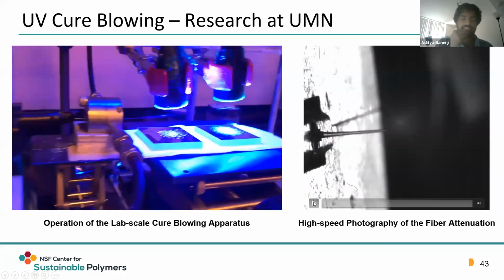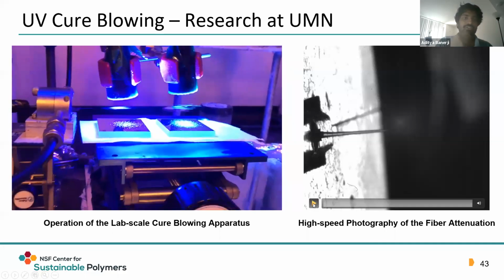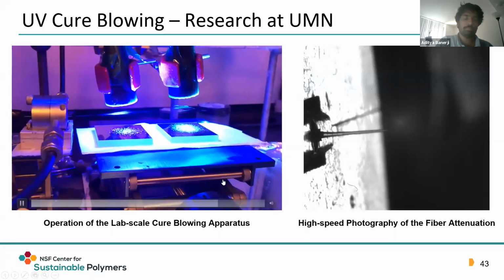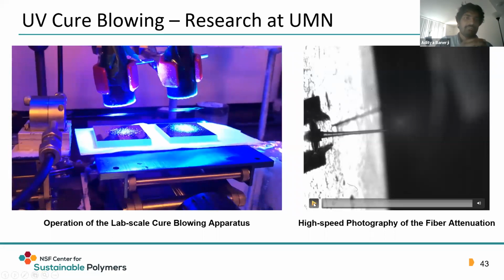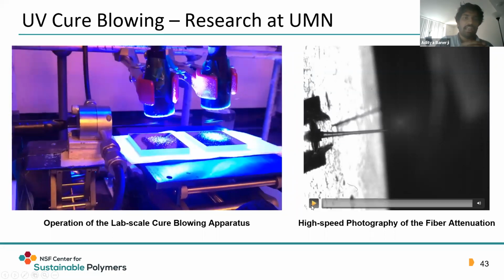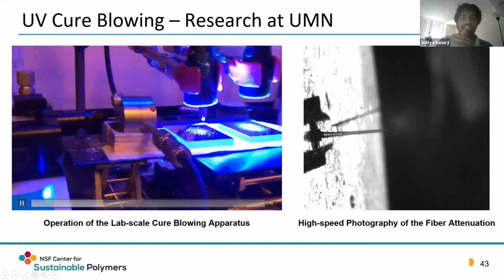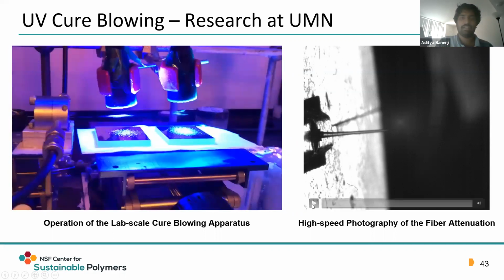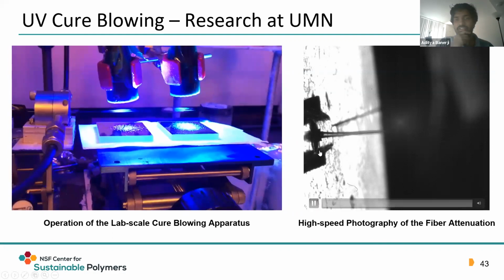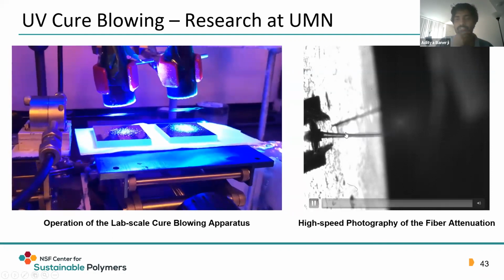blowing setup that we have in UMN in action, in which you can see that through the syringe on the left, the reactive monomers are extruded to the die, and during flight, upon shining UV light, they cross-link, which is collected downstream. While the video on the right basically is a high-speed photography of the fiber attenuation process that is happening, in which high-speed air is impinging on it from the top and bottom slits, leading to progressive thinning of the fiber jets as well.